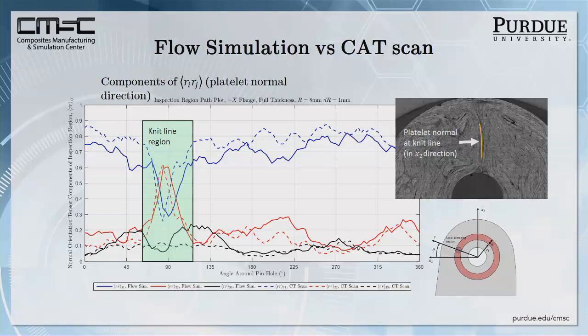orientation component, and that one should be parallel to this line, which is the X3 direction, and that's the peak. And then the one normal to the direction should take the minimum, and it does. And of course the outer plane should be relatively small. So this shows a very good relationship between prediction and observation in a fairly, I think, aggressive way. We've done many of these plots, and we keep surprising ourselves about how good this is.